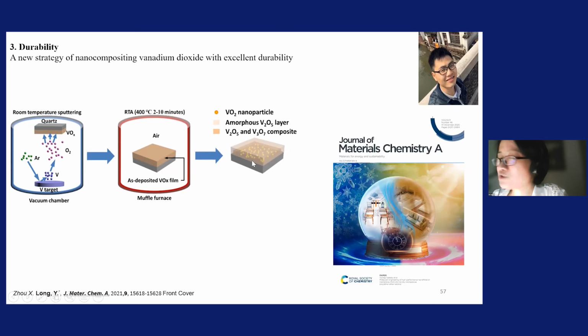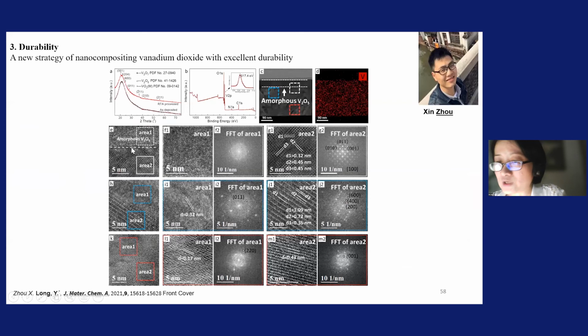But for this film, it was also very accidental. He came to my lab, he brought the sample, and we measured it for him. See here, this sample, even after 1 year, still has very, very high thermochromic properties. So it's more or less like an accident. Then we did the TEM, and we realized this VO2 is more or less embedded inside amorphous V2O5, because V2O5 is very stable. So that's why it can enhance its durability. Okay, so this is another one, trying to solve the durability issue and the scaling issue.